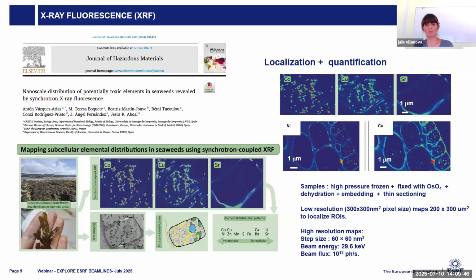So for this, you need to prepare your sample. Here it has been a full process with high pressure freezing, then osmium fixation, dehydration, embedding, and sectioning. And then when coming to the beamline, we can perform this first low resolution map to determine where we will then scan with the very small beam some regions of interest. Here you see on the top right the X-ray fluorescence mapping of, for example, cobalt, copper, strontium, and so on.